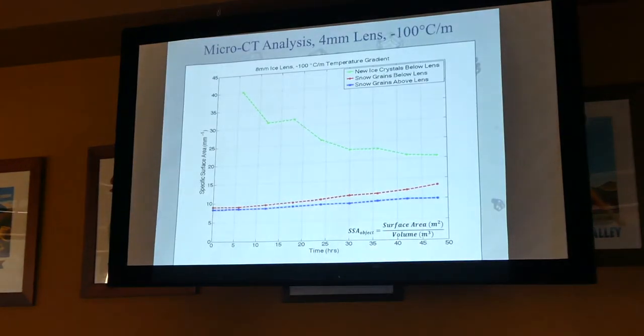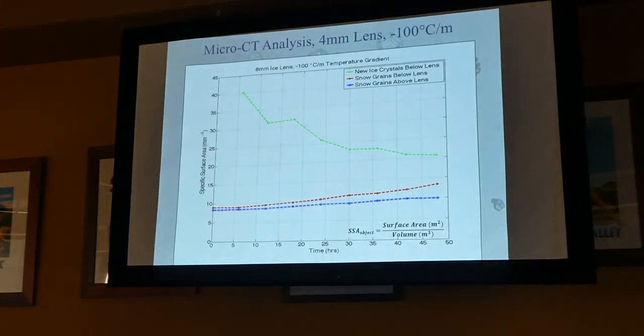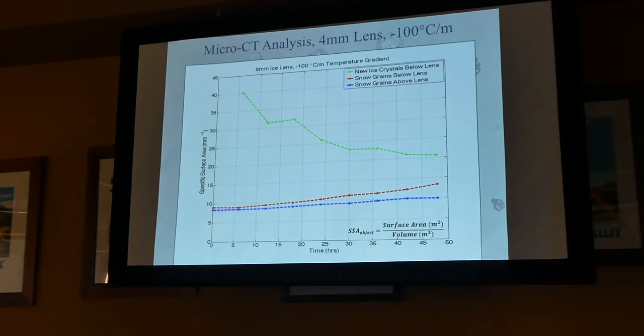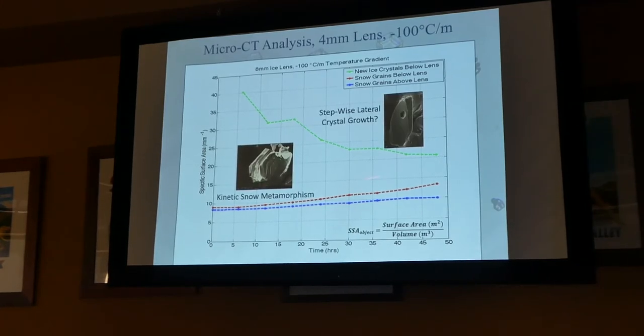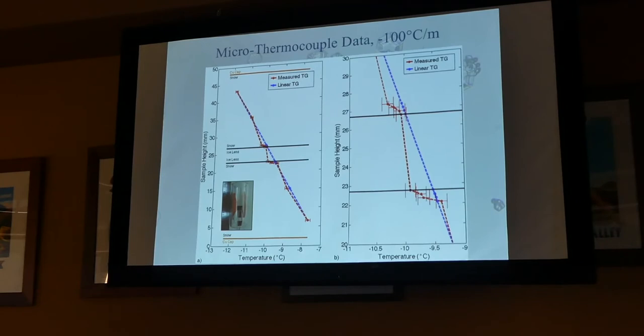And from the micro CT, you can plot lots of stuff and get lots of numbers. There's not much to learn here besides that a trend going up in the specific surface area is indicative of kinetic snow metamorphism, and going down for the new ice crystal growth is maybe stepwise lateral crystal growth. Just some things you can pull out of micro CT data. But the more interesting stuff that we looked at in the quantitative sense and plotted was the degree that this temperature gradient that we saw at the interface was greater than what was imposed.